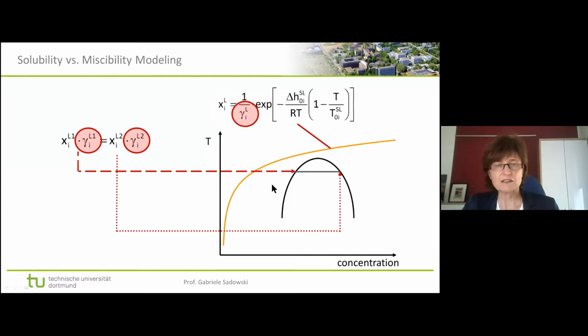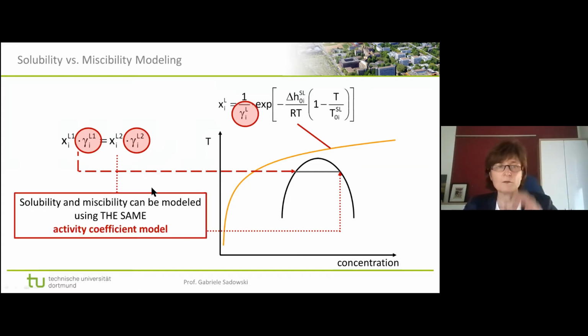And for the liquid-liquid demixing, you of course know that this is the type of equations to apply. So for every component, water, polymer, and API, we have these equilibrium conditions. And the nice thing is we have, again, to know what the activity coefficients are. So this is the same thing as we have here in the solid-liquid equilibrium equation. So that means miscibility and solubility can be modeled using only one and the same model for the activity coefficient. And of course, as a thermodynamicist, you know several activity coefficient models, and you could, in general, use any of those.